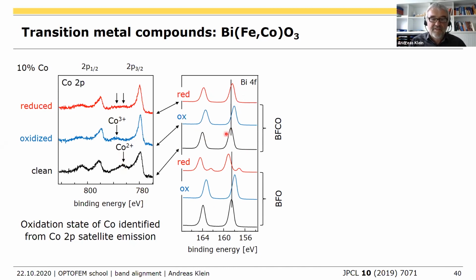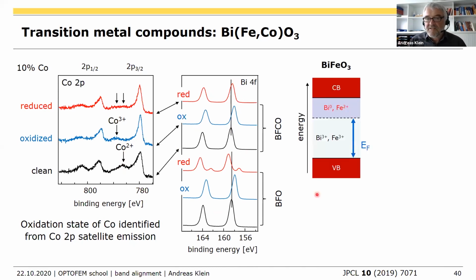And you see that the sample which is really reduced, where we see the metallic bismuth, now the Fermi level is really much higher than for this cobalt doped sample. So that's the situation for the bismuth ferrite. So our Fermi level can vary like this, and until we reduce our bismuth, we also reduce the iron. So that would be kind of an upper limit of the bismuth ferrite.